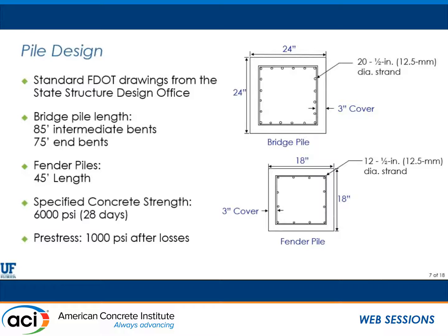So they said, let's just use a 24 inch as kind of our standard size pile. So we went with that. The pile lengths, there was no splicing required. So we cast the piles into 85-foot lengths for the intermediate bents and then 75-foot lengths for the end bents. And then the fender piles were a little bit shorter, easier to handle, and smaller. I went with the 18-inch standard piles there, the smallest piles that they typically produce in standard. Pre-stress level is about 1,000 psi after losses.